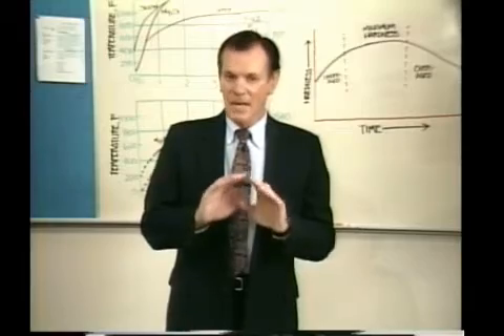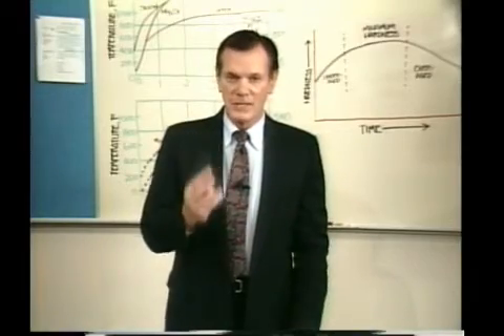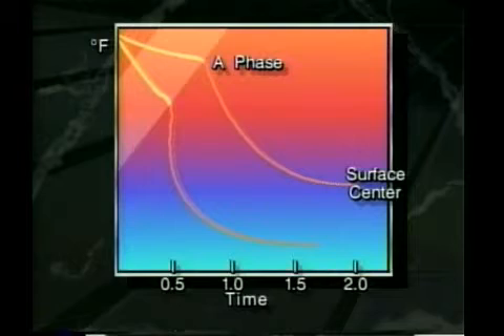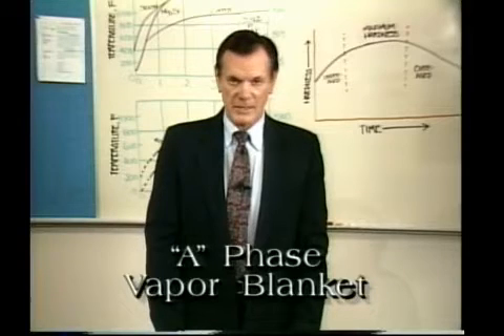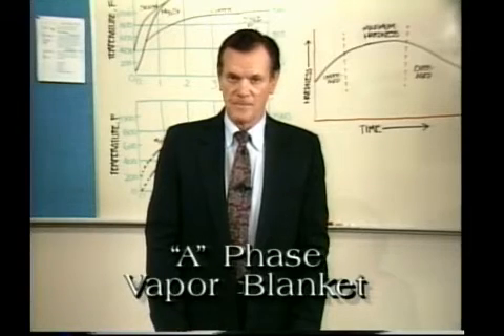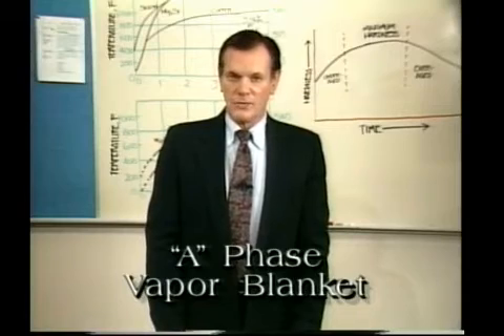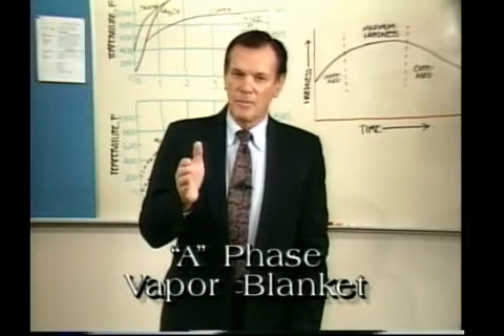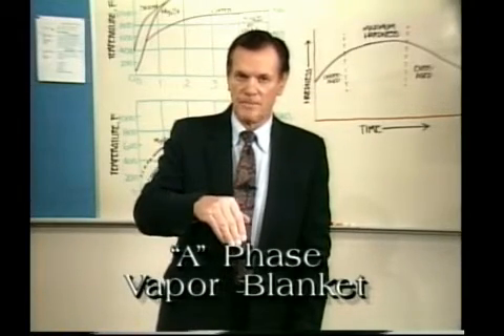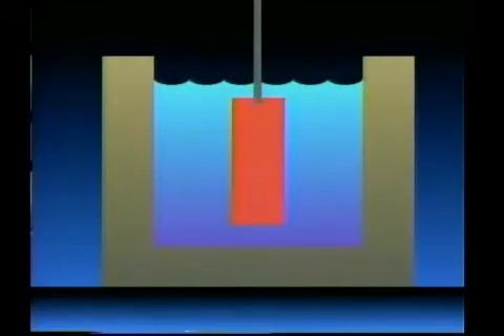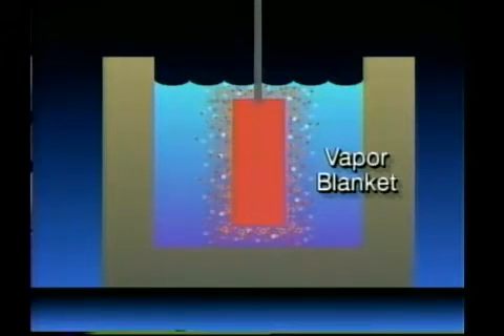During the quenching of any metal part, there are 3 stages of quenching which are illustrated on the cooling curve in the next illustration. These are the following. 1, the vapor blanket stage, the A phase. This is the first stage of cooling, which occurs just after a part is immersed in the quenching fluid. When an aluminum part at 1,000 degrees is quenched into a tank of water, the water that is in contact with the hot part instantly boils and quickly turns into a vapor.